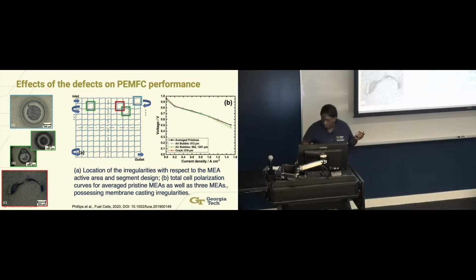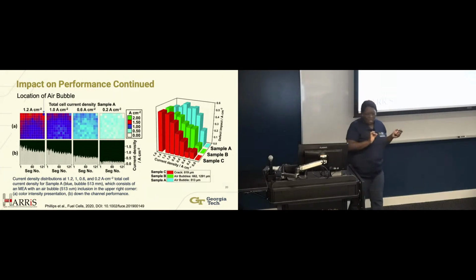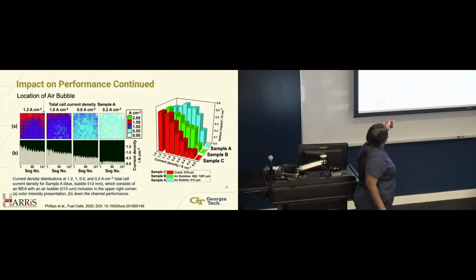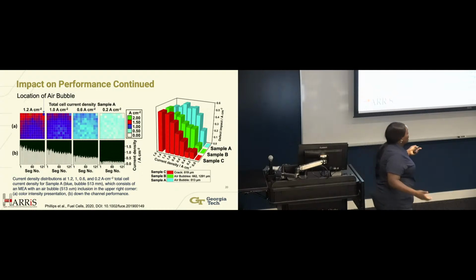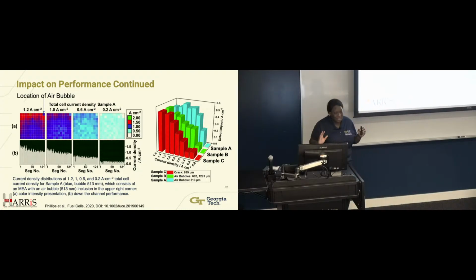We took this work a little bit further to understand when this is really happening. If we take just the one air bubble at the top and look at what happens to it as we go from a high current density to a lower current density, we see that there are impacts. This is the current density, this is the impact, and this is the sample. At the lower current densities, we see more losses, but at the higher current densities, it's operating well. So what we learned is that if we are operating at high current densities, there's limited to no effect from the defects that can be present, but they're more prominent in the low current density region.